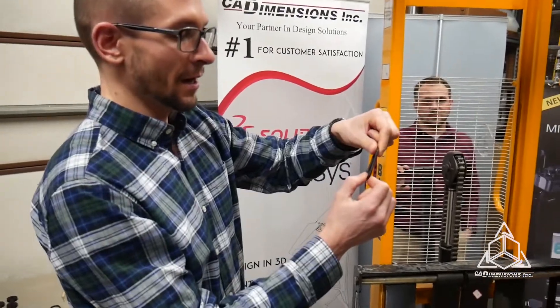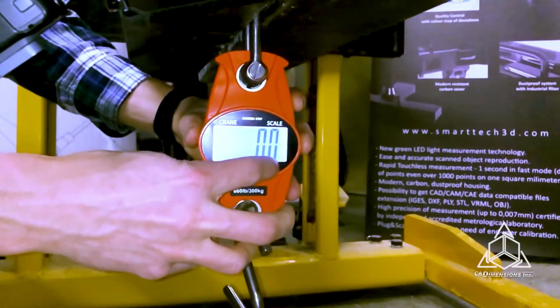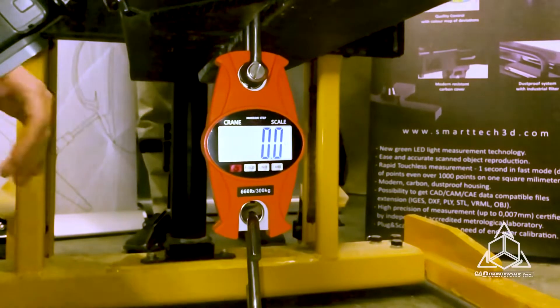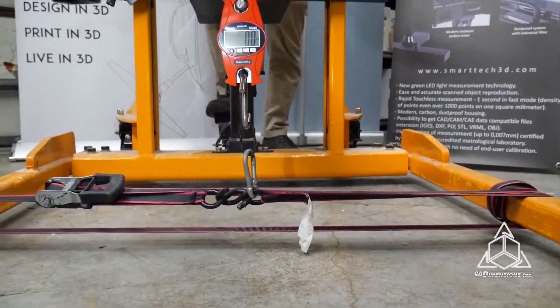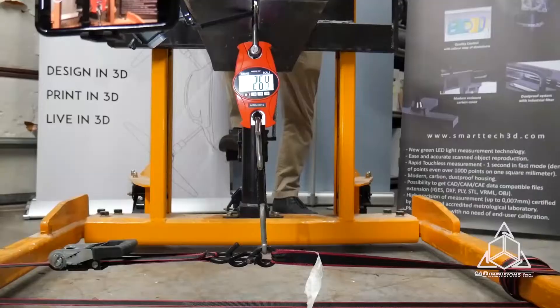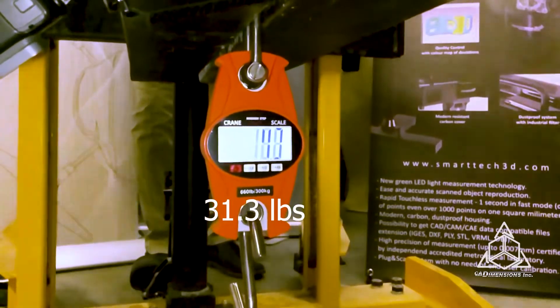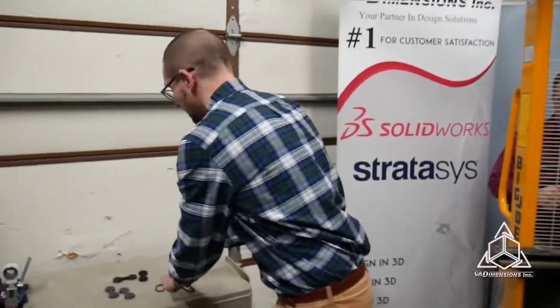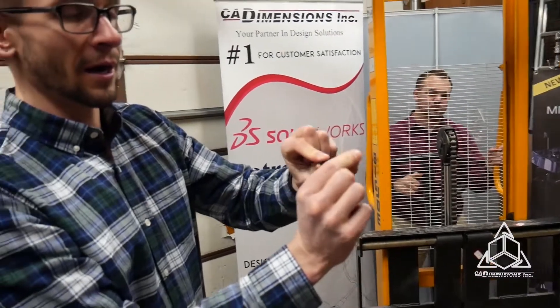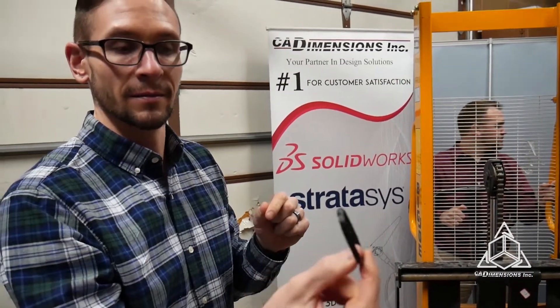Okay, so first we have the vertically oriented TPU ring. It broke — I don't know exactly what it was at but we have the recording. It was about 31 pounds. Let's go back and look at the official tape, but by the time you see this we'll know. 31 pounds — pretty easy snap. On to material number two, our horizontally layered piece of TPU material, which is what we tested in the previous video.